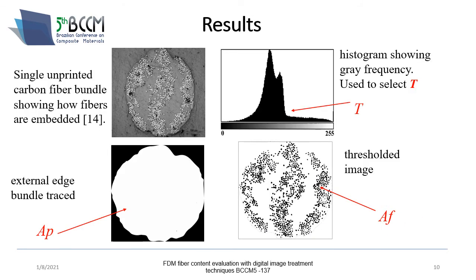For the results, we have here a micrograph of an unused carbon fiber bundle. Here we can see some porosities inside the filament, as well as the fibers grouped in clusters. The histogram showed the gray frequency, so the histogram was useful to determine the appropriate threshold value. This threshold value was useful to determine the perimeter of the bundle. And then we use the line edge detection to differentiate between fibers and matrix.